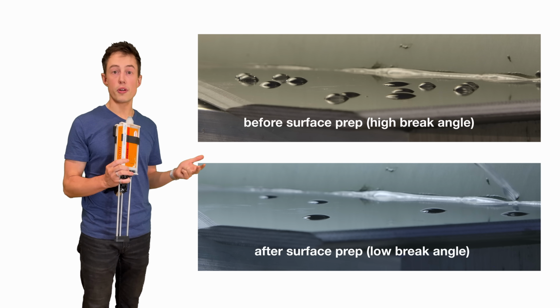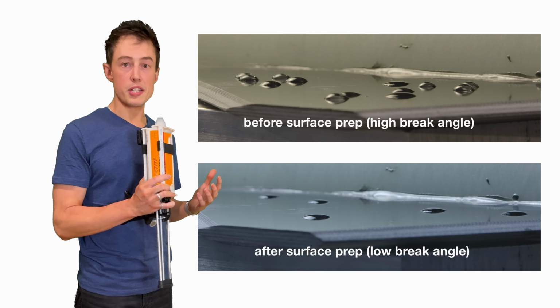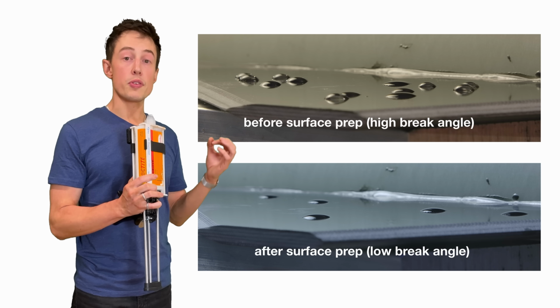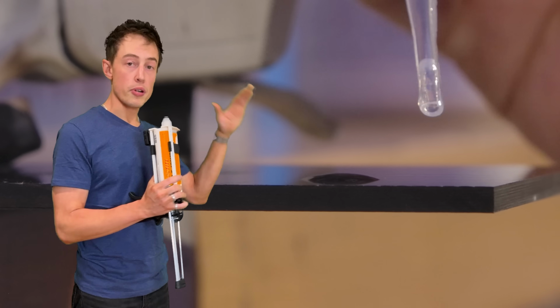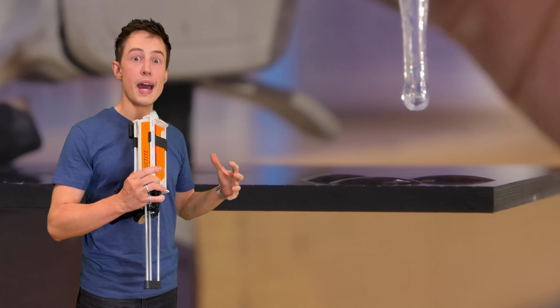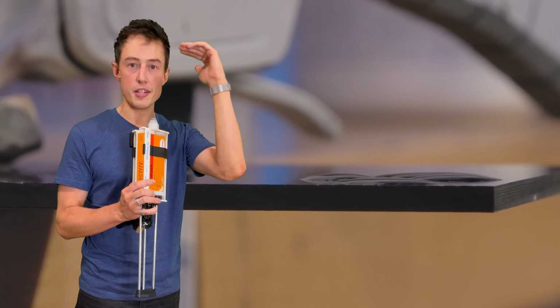You can test surface energy using a water break or contact angle test, and we've done this in past videos before. By putting water droplets on the surface of a material that you've just recently prepped, if the water spreads out and has a very low break angle, that means the surface is pretty active. It has a high surface energy and it's ready to bond with.